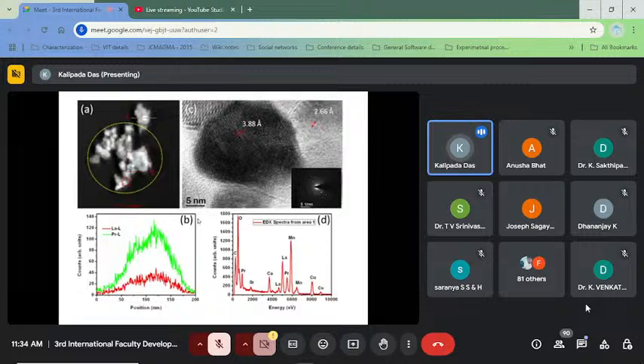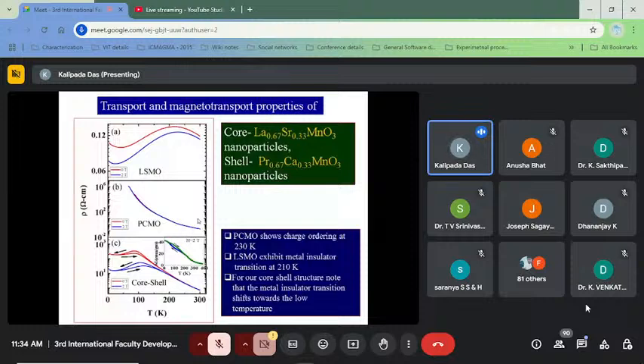And the characterization showed that yes, this is LSMO and this is PCMO. So within the PCMO matrix, LSMO nanoparticles are incorporated. Now we measure its electron transport properties in the presence and in the absence of an external magnetic field. This is the basic LSMO. Temperature dependent resistivity shows, as usual, a metal insulator transition, and below this transition it behaves like a metal.